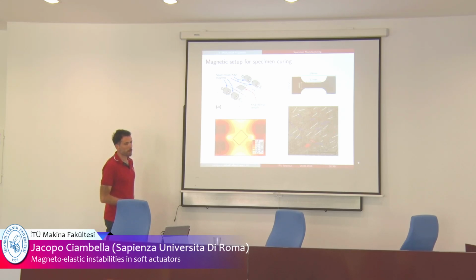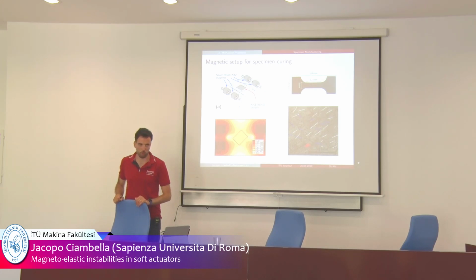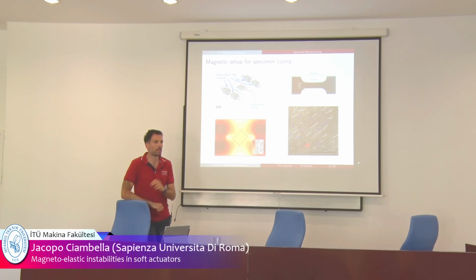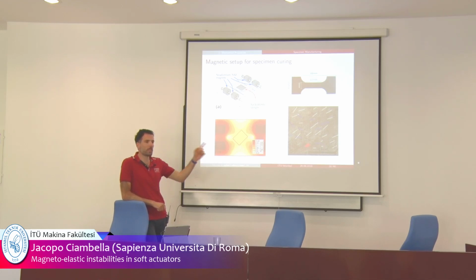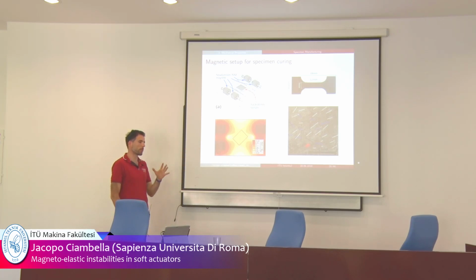This is a micrograph. Okay, we use carbon fiber also for another reason, because we started playing with carbon nanotubes, because you can get nickel-coated carbon nanotubes. But the problem with nanotubes is that it's very difficult to control the orientation, and not only control the orientation, but to see the orientation of the nanotubes. To check if the nanotubes are oriented, you need much more complicated equipment. Here it is simply a microscope. Okay? You can see the orientation of the fiber almost with the naked eye. This is 1 millimeter, for instance. So the mechanical properties.